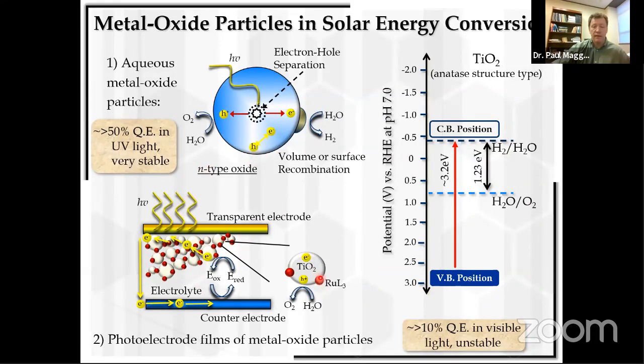But the reason that you have to put the little molecular dyes onto the surface is that all of the stable semiconductors for this approach have a large band gap. And so what I've shown on the right here is the band gap structure, the valence band and the conduction band position for TiO2, and their energetic position with respect to the relevant redox couples. And in particular, water oxidation here in the light blue line, and then water reduction in the dark line here